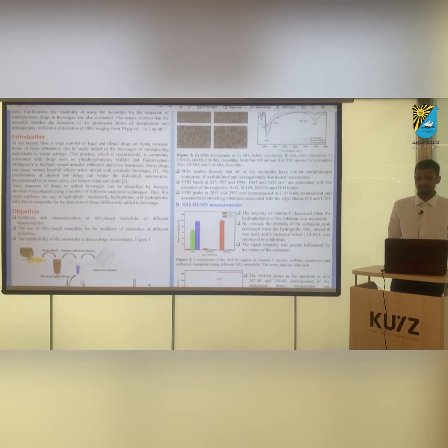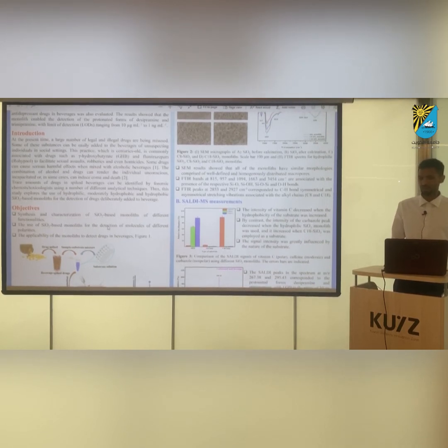The result clearly demonstrates that the intensity of vitamin C decreased when the hydrophobicity of the substrate was increased. On the other hand, the intensity of the caffeine peak decreased when the hydrophilic silica monolith was used, and it increased when the C18 silica-based monolith, which is hydrophobic, was employed as a substrate. Thus, the signal intensity was greatly influenced by the nature of the substrate.